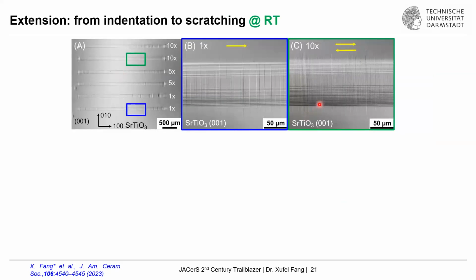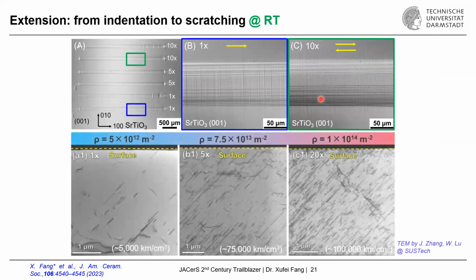This time, we do not use the chemical etching technique anymore, but rather directly show you the transmission electron microscope images, taken from samples perpendicular to the surface within the wear track. You can see that after 1 cycle, the dark lines are the dislocation lines. We have a couple of dislocation lines, and after 5 cycles, many more, and 20 cycles, way more than what we can imagine even before we see these images. Just to give you a brief idea, here we have roughly almost 100,000 kilometers length of dislocations within 1 cubic centimeter. We would also like to point out that there is no crack formation in this case, and we achieve all this at room temperature. And this is the case study on strontium titanate.